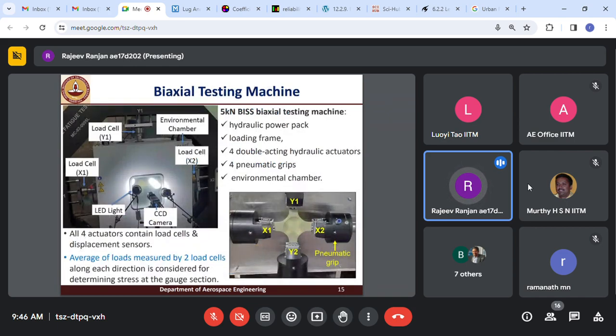Biaxial tensile tests were conducted on a 5 kN BISS biaxial testing machine, which contains a hydraulic power pack and a loading frame on which 4 double-acting hydraulic actuators are mounted, and each hydraulic actuator contains pneumatic grips which hold the specimen during the experiment. Since we conducted experiments at controlled temperatures, an environmental chamber was there to do that. All 4 actuators contain load cells and displacement sensors. In this study, the average of the load measured by 2 load cells along each direction is considered for determining stress at the gauge section.